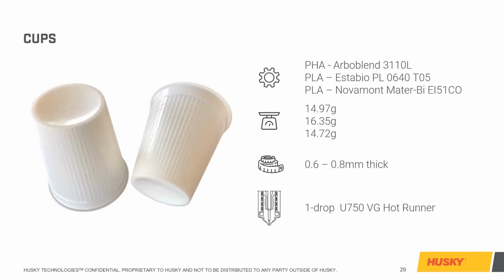This one here, a customer ran several different resins, a PHA and a PLA, with two different PLAs from two different manufacturers, three different part weights, so 14.97 gram, 16.35, and 14.72, about 0.6 to 0.8 wall thickness, and this was also a single cavity.